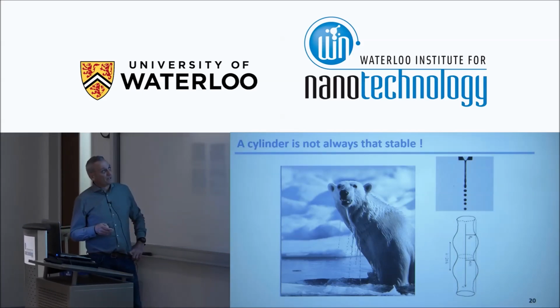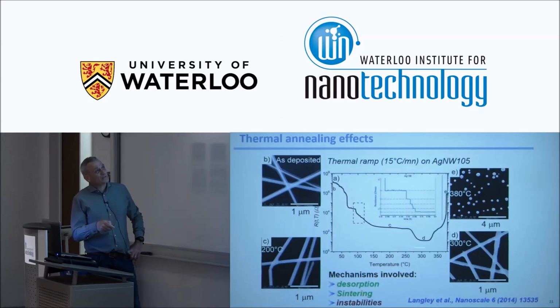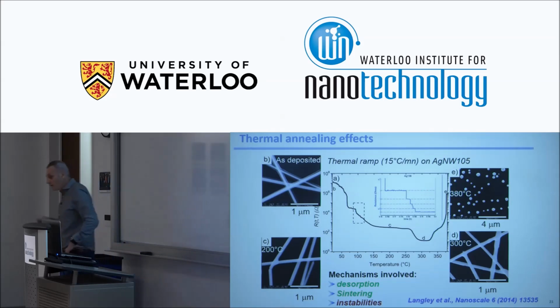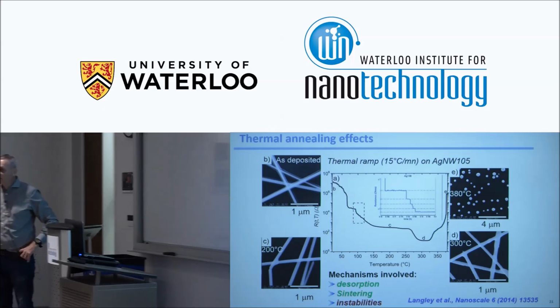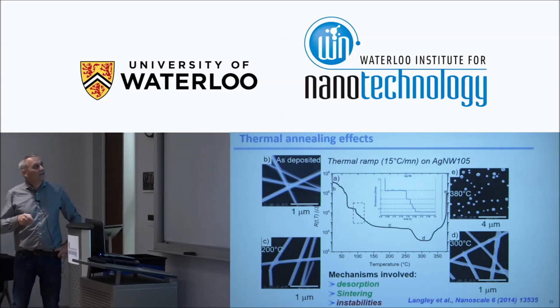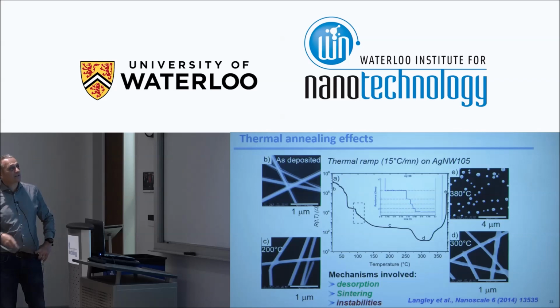So we guessed that we would have something like this, but we didn't guess at all that from time to time we have a kind of discontinuous decrease of the electrical resistance. For example, during the increase of temperature, we can observe the discontinuous decrease, or as well, if we are at constant low temperature, let's say 100, 120 degrees, especially for a network which has a low network density, just above the critical density, we observe this kind of discontinuous decrease like this.